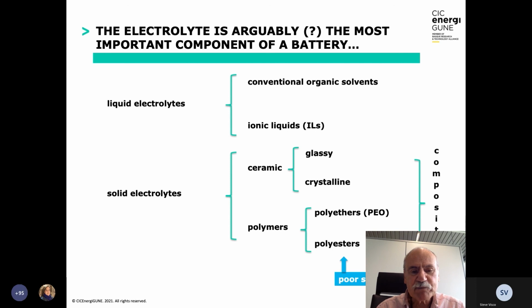And the problem with polymer electrolyte is that polyesters are not stable versus lithium metal or sodium metal, and polyethers tend to have a low conductivity at room temperature and a low transport number. The fraction of the current which is carried by lithium is less than unity, close to about 20%, which is a disadvantage, as I will show. In fact, there are only a few batteries with polymer electrolytes which are commercial, of course, in addition to the conventional organic solvents, which represent 99.5% of the batteries made.